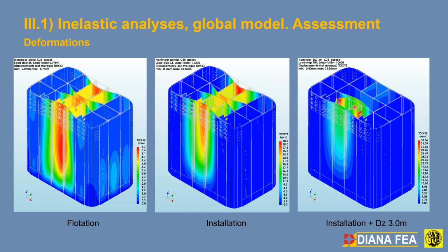Now, if we allow this to overfill by 3 meters differential, the deformation pattern changes. We still have a 30.3 millimeter drift in this direction, and actually less, it's in the green area, so it's actually 23. But now we have a bulging out of plane of 33 because of the differential of 3 meters in the top. So the fact that this chamber here overflowed while the caisson was already inside the water changes completely the deformation shape and the critical forces here, as we will see.